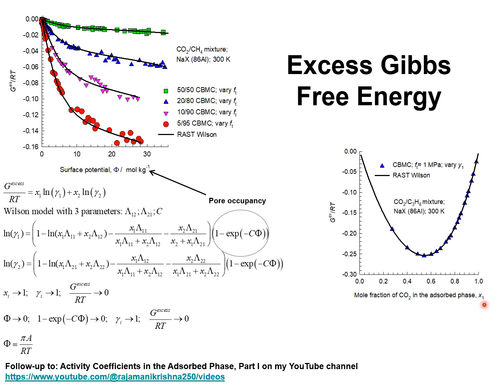The message that was conveyed is that the excess Gibbs free energy for the adsorbed phase is a function not only of the composition in the adsorbed phase, x1, but also of the surface potential. And we need to set up the Wilson model, say, with 3 parameters, lambda 12, lambda 21, and the constant C.